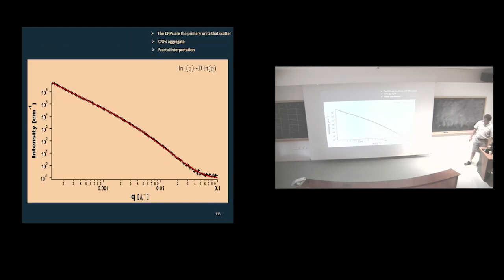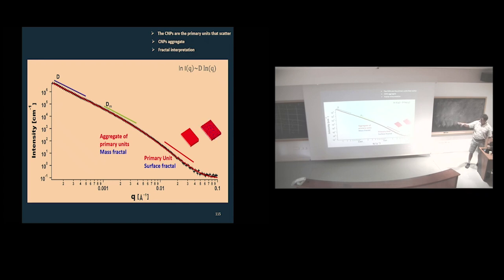Almost there. The story comes here. So this is the end of the story of USAXS. And here we have the scattering pattern. We have a lot of data behind this, but his simulation is, at the beginning you have the primary unit is a surface fractal, Porod usually. Then you have a mass fractal, the aggregates, which are the aggregates of the primary units. Then you have something that could be like a surface or mass fractal, and these things can be smooth, they can be rough, they can be diffuse, depending on the value of that slope. And he interpreted that as covered with oil or not covered with oil.